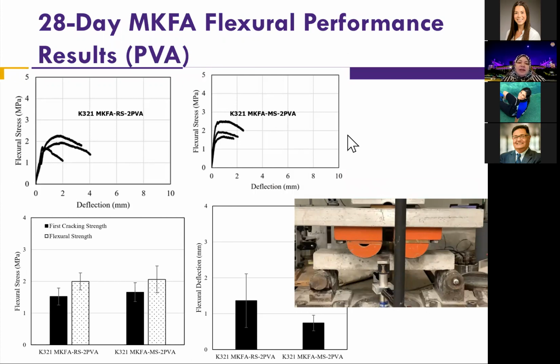Unfortunately, the metakaolin fly ash combination did not perform well. As you can see, it's behaving like regular concrete. It gave us a single crack when we did the flexural performance test. So to date, this is not behaving like an ECC, but we are going to start working on varying the percentages of metakaolin fly ash.